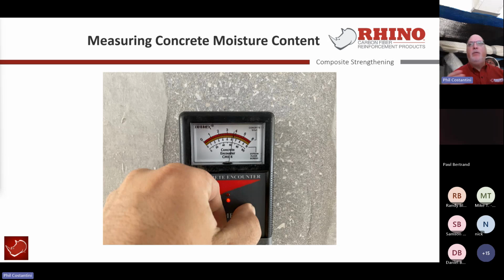So if you're in an environment that's 5% or higher, it's important to get that area drier than that 5% content, whether you use blowers, whether you use heaters. And it's not good enough just to take a torch or a big high pressure air dryer and dry the concrete. No, it's the entire environment that has to be controlled to sustain that 5% or less moisture content in concrete prior to applying any epoxies. The reason being is if you shut that heater off or you shut that blower off, the moisture is just going to come back as you're applying. So make sure it's always running for at least a 24-hour period while you're working in that environment that's got high sensitivity of moisture in the wall. So once again, the critical path here is 5% or less moisture content in order to have a successful bonding adhesion for the epoxy.